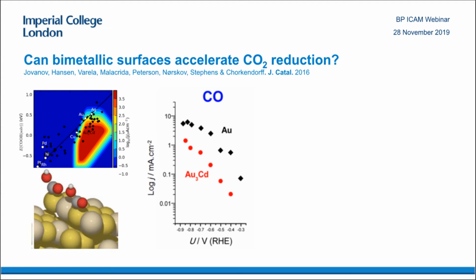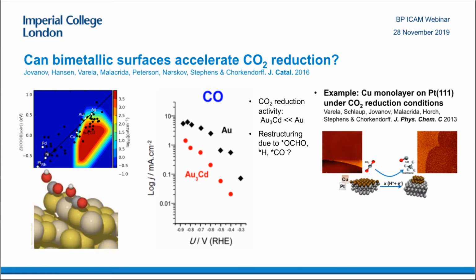Whatever we did, what we found was that the reaction rates were a lot lower than gold. This was a really big disappointment to us when we were measuring the amount of CO being produced. So what we think is that we're not able to realize this idealized structure here. This is exactly what we found as well when looking at other bimetallic systems. For example, we put a copper monolayer on platinum.